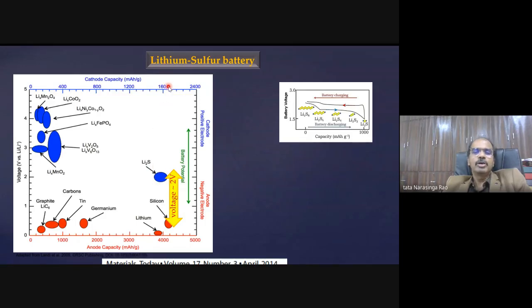My God, it is so many times higher, but its voltage is less. It's only 2 volts versus lithium. But if you take lithium cobalt oxide, it is 4 volts. I am compromising on the voltage by half, but I am increasing the capacity multiple times. So the total energy density is capacity times voltage, and if you multiply, sulfur gives very high energy density that can be stored.